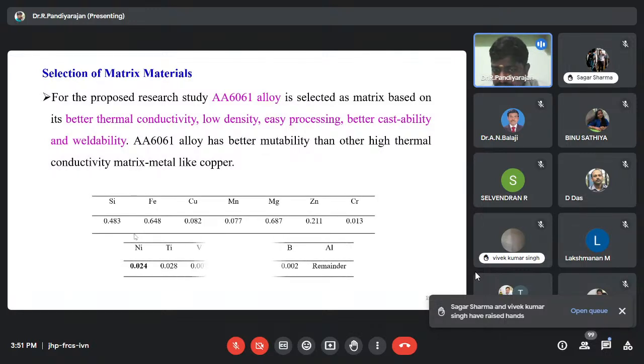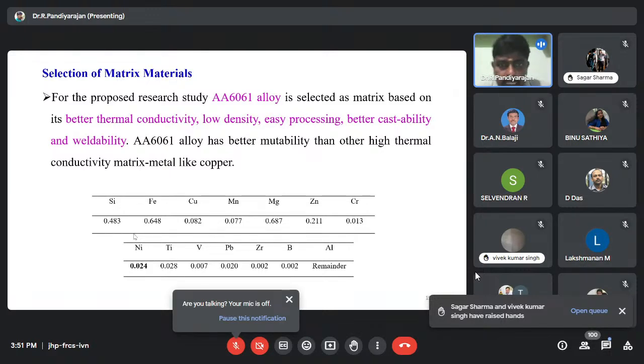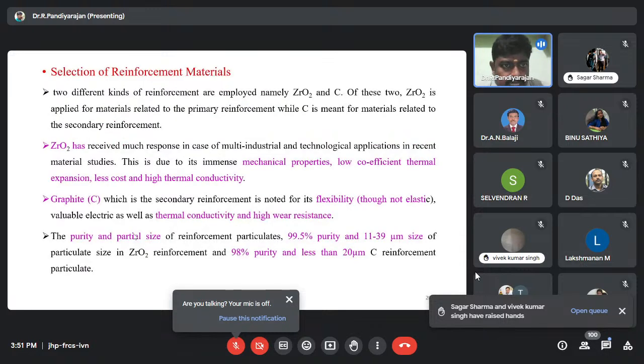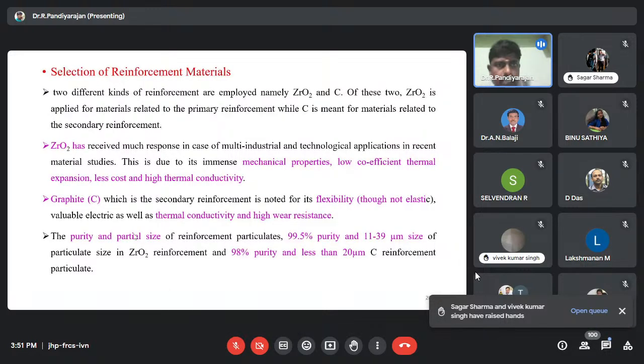This session I will consider only AA6061 alloy, a basic wrought alloy. AA6061 alloy is selected as the matrix based on better thermal conductivity, low density, easy processing, and better castability and weldability of the material. Once we buy the AA6061 alloy, we definitely have to find the percentage of each composition in the material: silicon, iron, copper, magnesium. You find the composition by spectrometer analysis and confirm the wrought alloy AA6061.